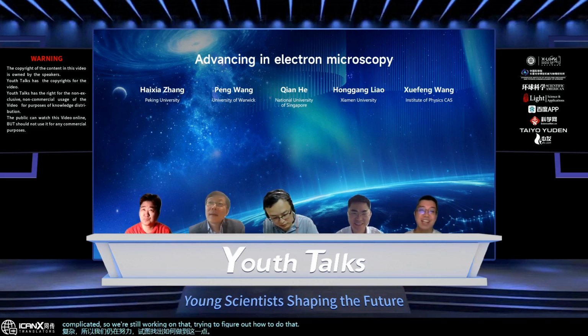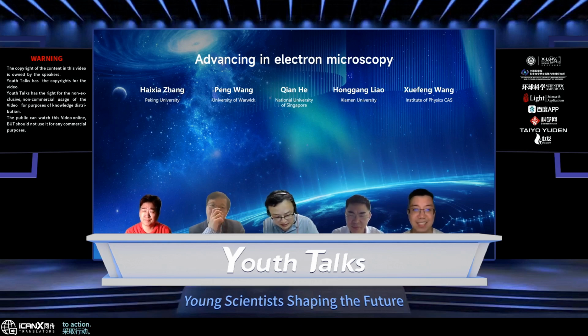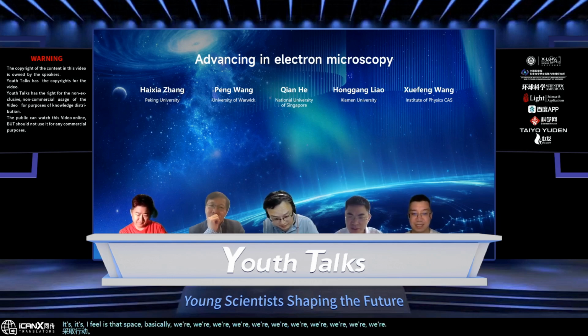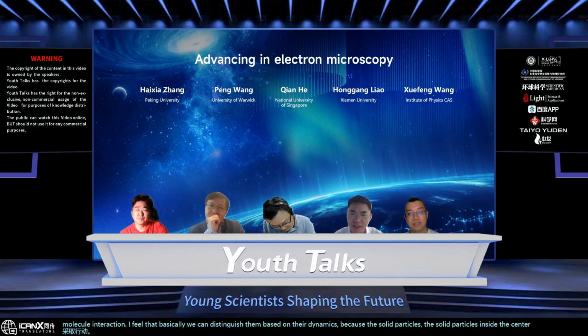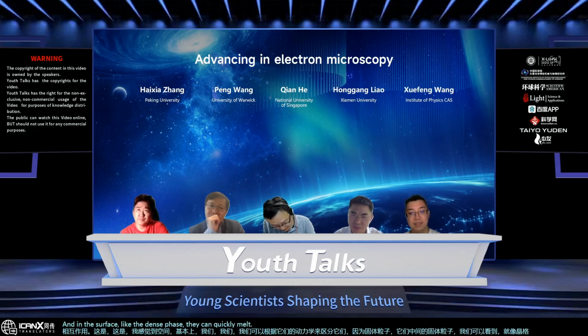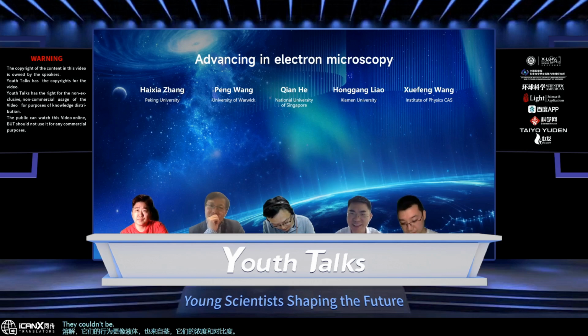Okay. Did you notice any interaction between the liquid and the solid at the interface? The molecular interaction. I feel that basically we can distinguish them based on their dynamics, because for the solid particles in the center we can see the lattice fringes, while the surface dense phase can quickly dissolve once the structure changes, like when the particle shape and structure change. Their behavior is more like a liquid. Also from STEM, their concentration and contrast show they couldn't be solid. Okay, it seems complex and very interesting.